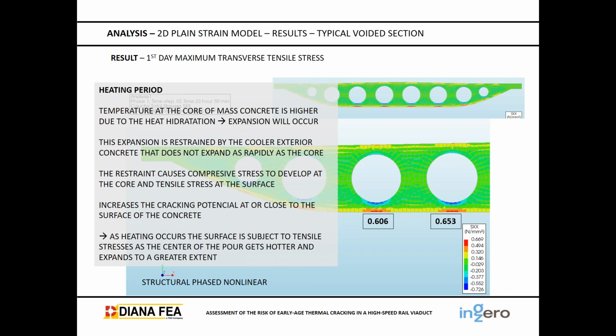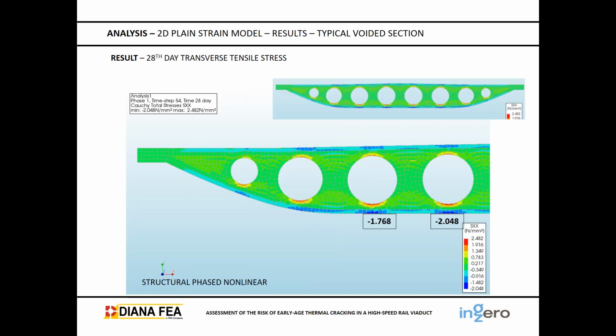So as heating occurs, the surface is subject to tensile stresses, and the center of the pour gets hotter and expands to a greater extent, okay? We see how the stresses develop over time, and if we have a look at the 28th day, the transverse tensile stresses disappear and become compressive stresses, so negative stresses, as we can see here. So that indicates that if something has happened due to the tensile stress, if a crack has opened, it's going to close and be in better condition, okay, as time goes by.